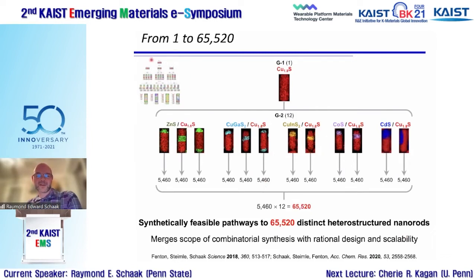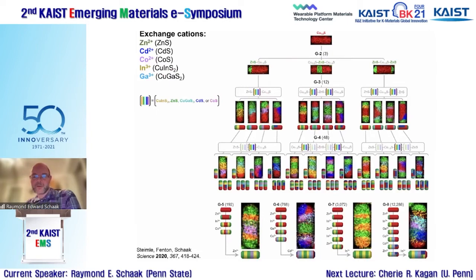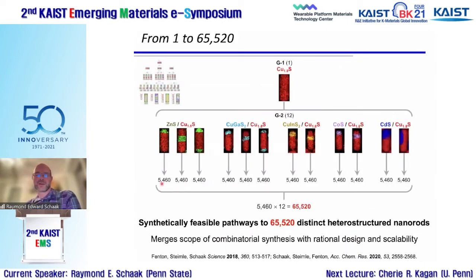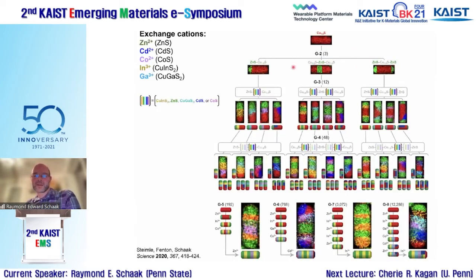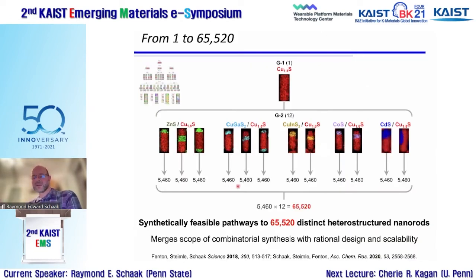And so this graphic that I had on the last slide, I was showing three second generation particles that we were starting with that had these three variants of zinc sulfide, copper sulfide. It turns out that we can make 9 other variants in reasonably high yield with high confidence. And so if you go back to this, basically each arm just starting with one of these gives us 5,460 possible derivatives. So each new structure that we can make at this level adds another 5,460 to the number of possibilities. And so we can in total at this point make 12 variations in reasonably high yield that we're confident in, which effectively lets us propose synthetically feasible pathways to any one of 65,520 distinct heterostructured nanorods.